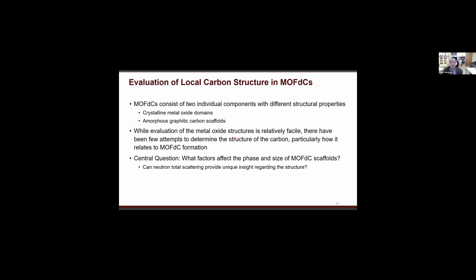So when we evaluate the local carbon structures in MOF-derived carbons, it consists of two individual components with different structural properties. One is the crystalline metal oxide domains, which is very straightforward, and the other is the amorphous graphitic carbon scaffolds. We need to evaluate both. The evaluation of the metal oxide structure is relatively easy, but there have been few attempts to determine the structure of the carbon, particularly how it relates to MOF-derived carbon formation. So the simple question is: what factors affect the size and the phase of the MOF-derived carbon scaffolds? Can neutron total scattering provide unique insights regarding the structure? This is the question to answer.